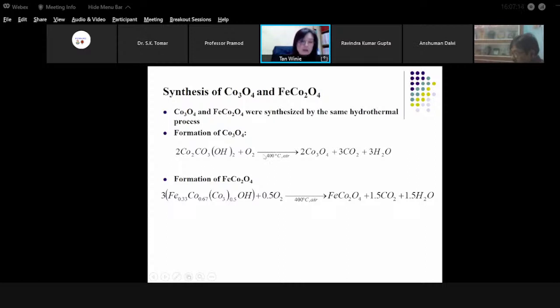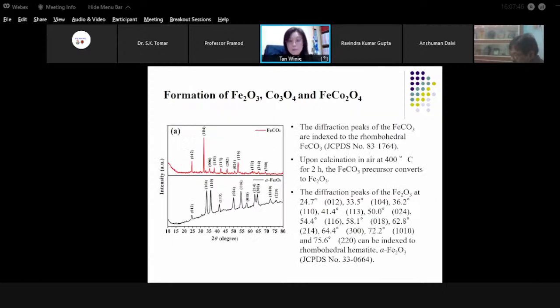So this first equation represents the formation of the cobalt oxide. For the synthesis of iron cobaltite, the same procedure was employed, but now in the presence of both iron chloride tetrahydrate and cobalt chloride hexahydrate. Different starting materials are used. This second equation represents the formation of the iron cobaltite. So we synthesized two single oxides and one iron cobaltite, and we also investigated their structural properties.